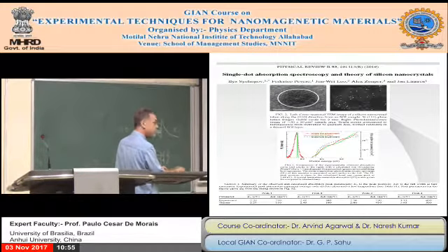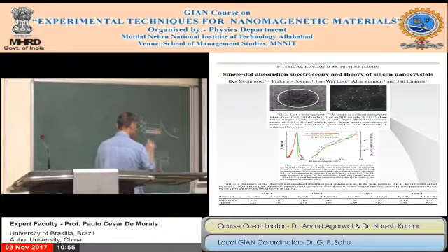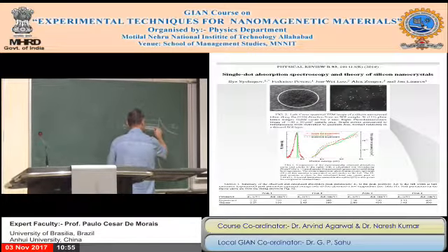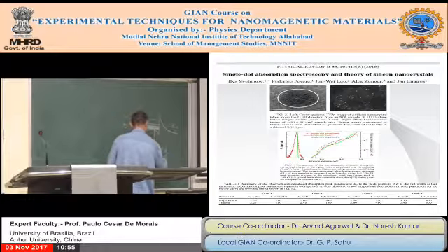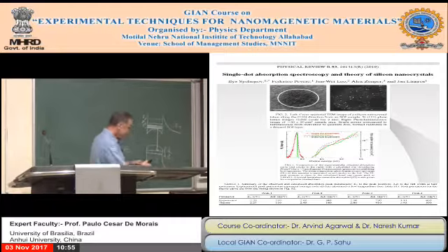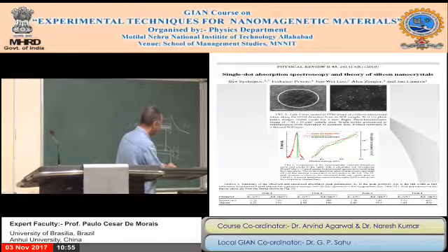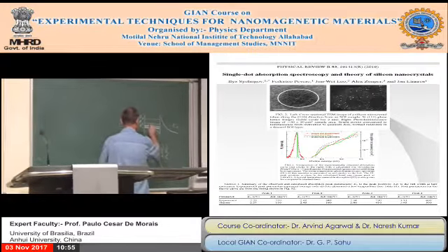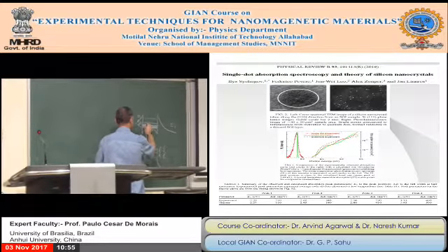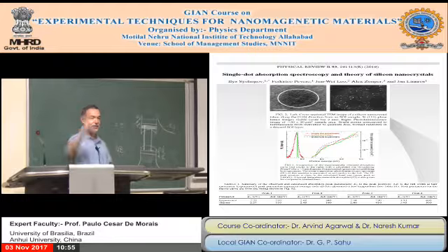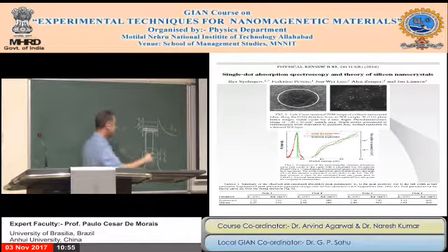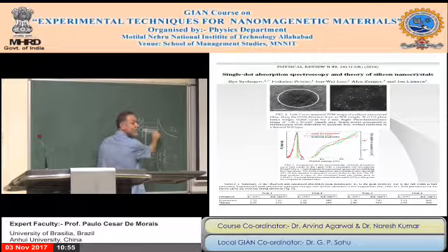That transition, the PL transition, likely is the transition from the bottom to here. And the first absorption is the absorption from this light hole to the top of the first band, to the Fermi level, because the electron cannot come to the bottom.